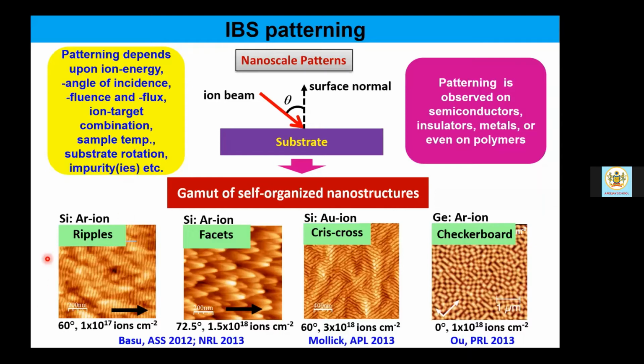For instance, this leftmost frame utilizes an angle of incidence of 60 degree, and how it is defined is shown here. So with respect to the surface normal, the incident beam direction makes an angle theta, which we talk about as 50 degree or 60 degree or whatever. On the other hand, these facets were formed corresponding to 500 electron volt of argon ion bombardment on the same silicon surface, but at an incident angle of 72 degrees.